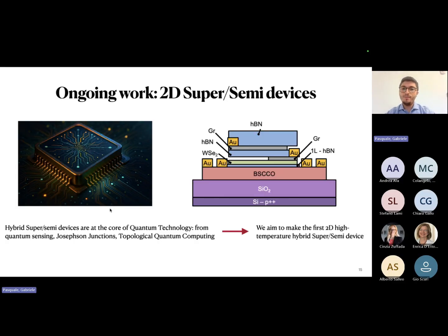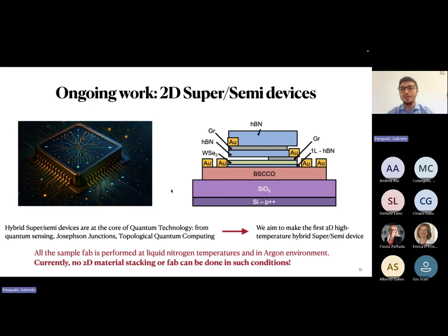So therefore, now what we aim to do is to really make the first two-dimensional high-temperature hybrid super semi device, combining BSCCO with two-dimensional semiconductors. Now, it sounds really good in theory. However, there is a very large limitation, which is that BSCCO degrades at room temperature, in air, and with moisture. Therefore, what this means is that we need to have a complete stacking and fab process that happens at liquid nitrogen temperatures. And to this date, there is no fab that can be done in such conditions for these materials.